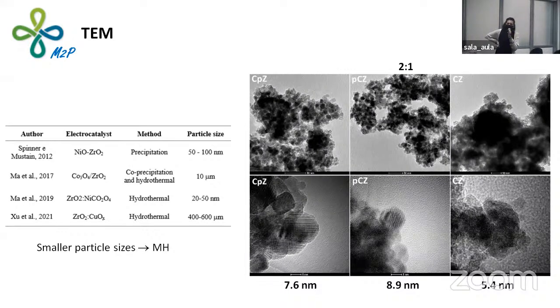were able to measure the average particle size, and for CPZ we have 7.6 nanometers, PCZ 8.9 nanometers, and for CZ 5.4 nanometers, all of them really smaller than what was found in literature, again, because of the use of the microwave hydrothermal. In literature, they all use conventional hydrothermal, precipitation and co-precipitation.